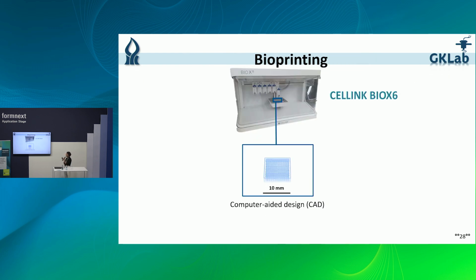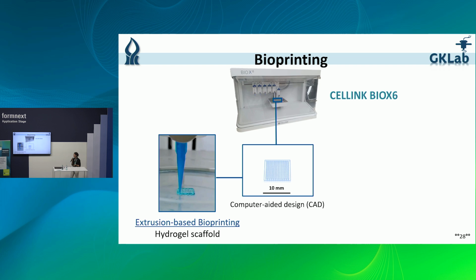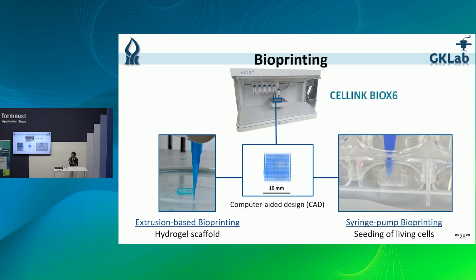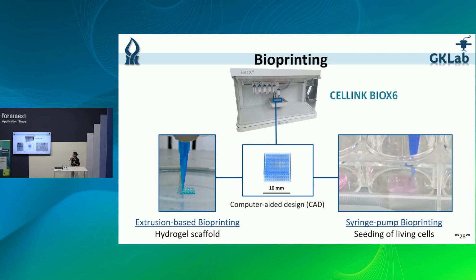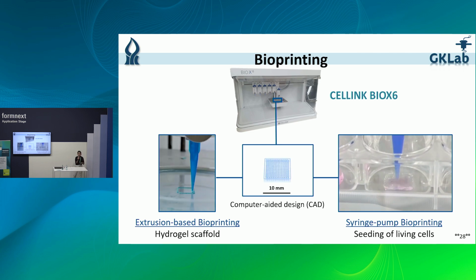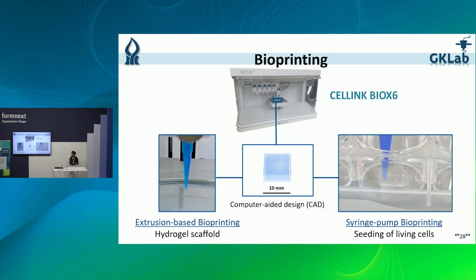So for the printing process, we use the Cellink Bio X6 bioprinter. It has several printheads and functions that I'll show you in a minute to deposit the materials in a controlled manner. The first function that we use is for the bioink scaffold, and we use extrusion-based bioprinting. We push our bioink through the nozzle using pneumatic pressure. And the other function that we use is syringe pump bioprinting, which we use to seed the cells onto the bioink scaffold.